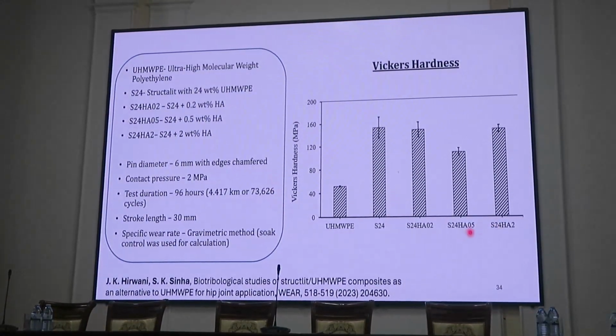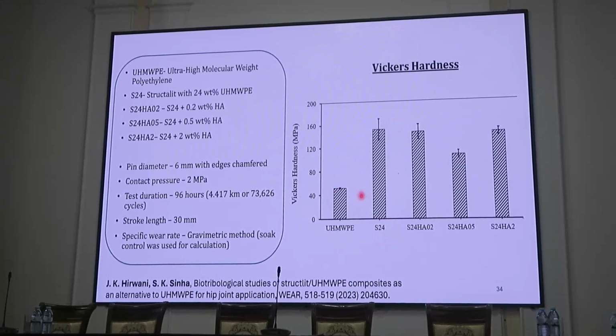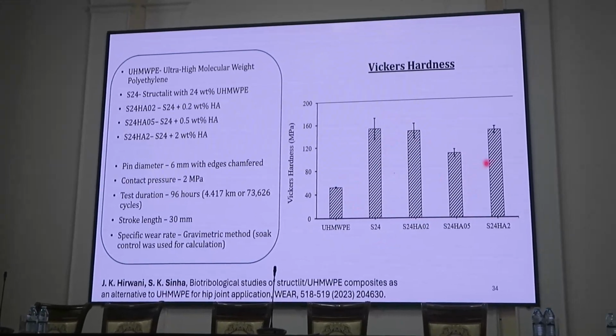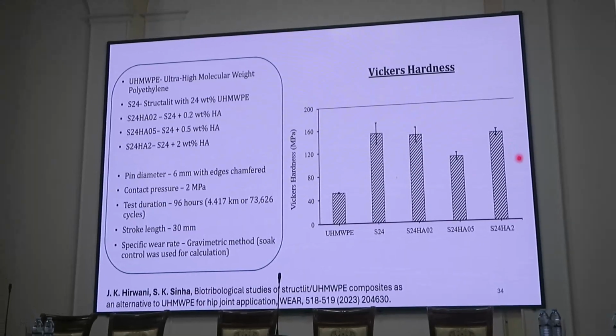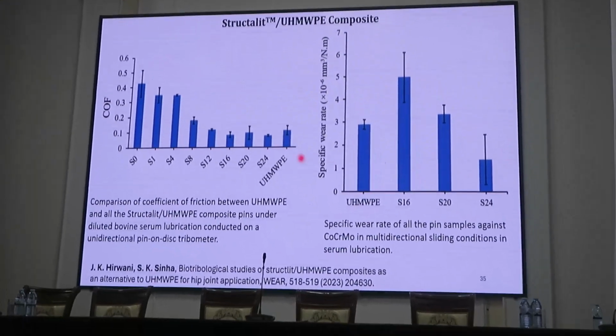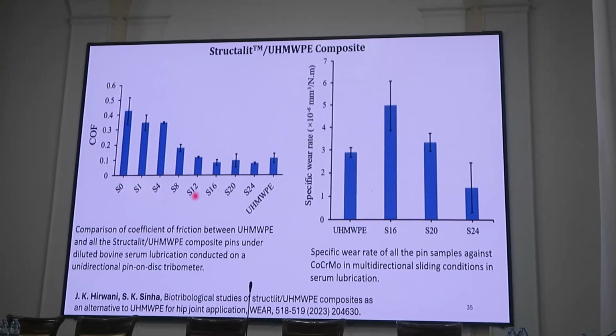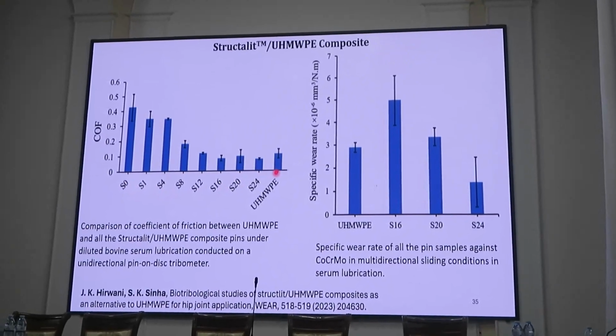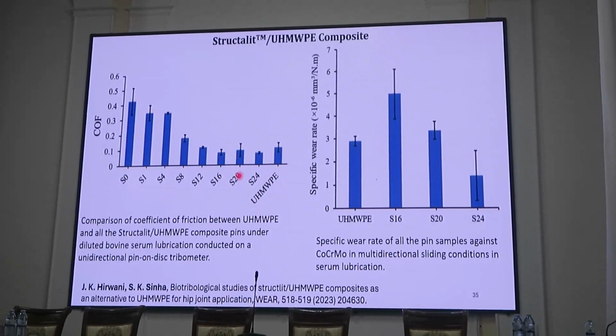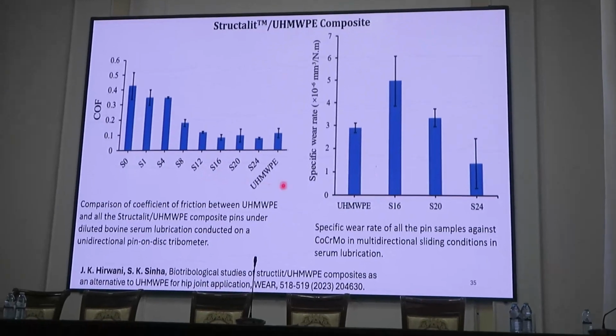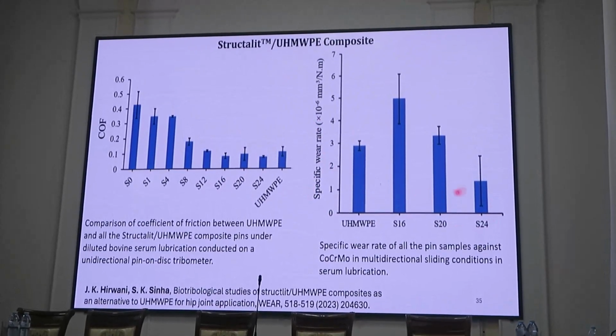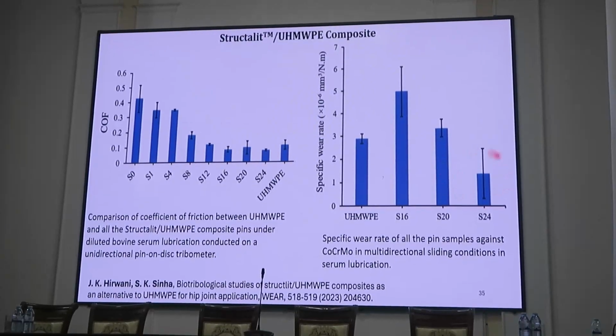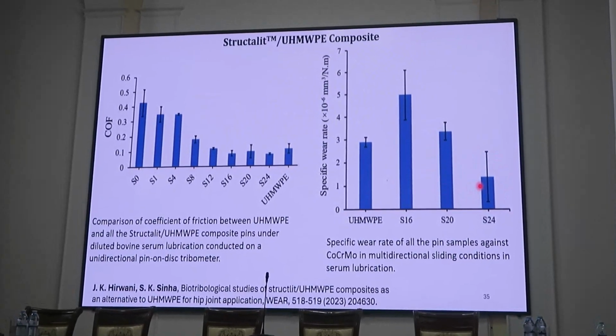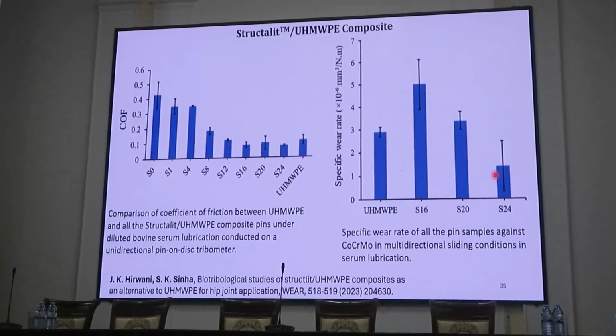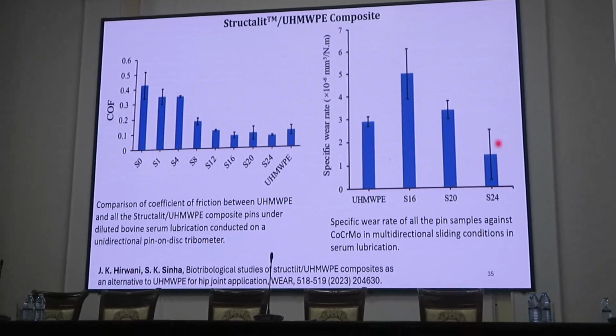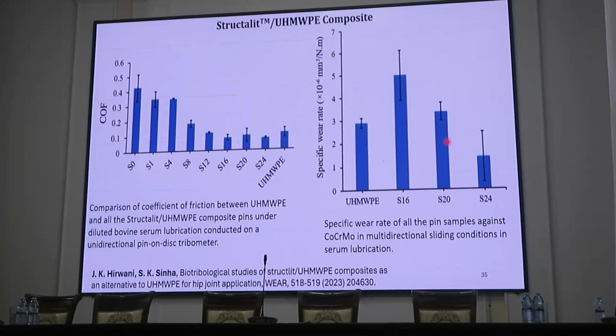So in some Vickers hardness tests we compared with UHMWPE. They have better results, better mechanical strength, and in terms of coefficient of friction, they can be slightly better than normal UHMWPE. So they have a lot of potential, and the specific wear rate is also low. Of course, these kinds of tests are quite complicated, but we have been able to get some initial results on these.